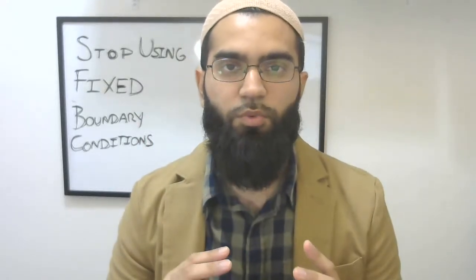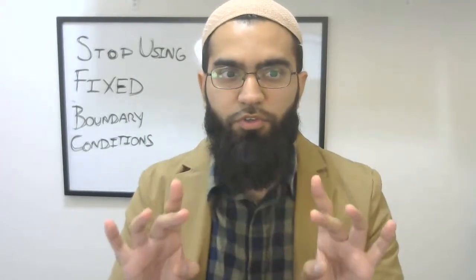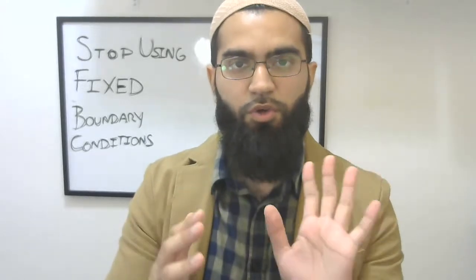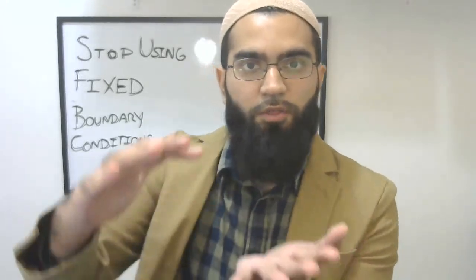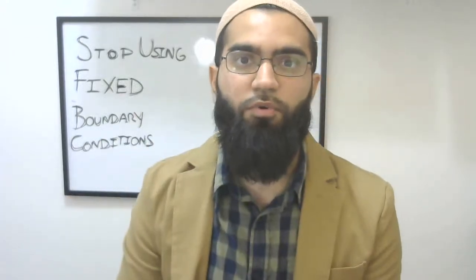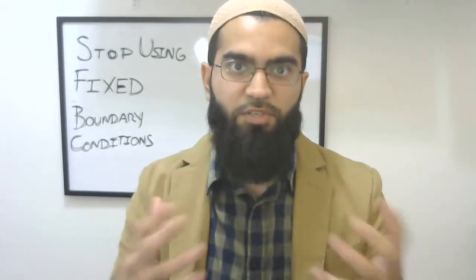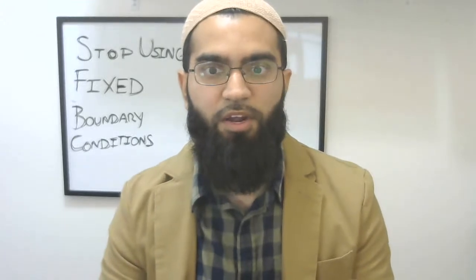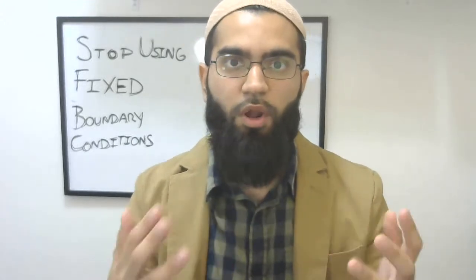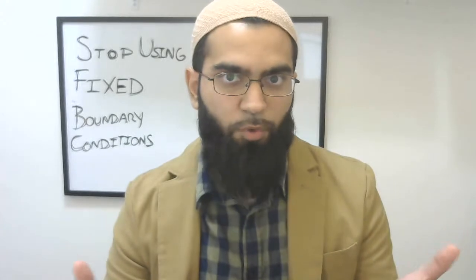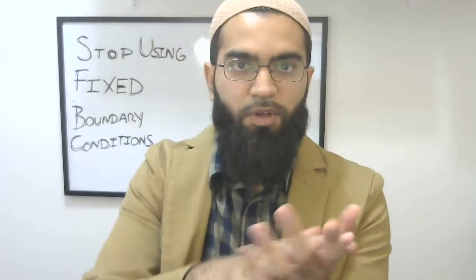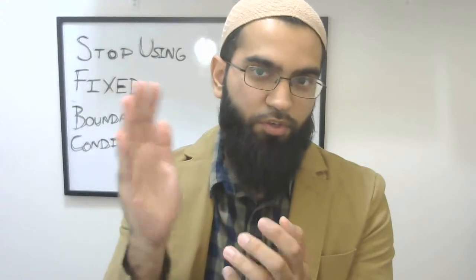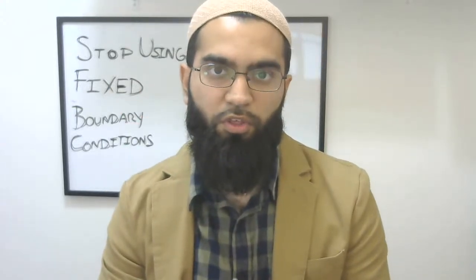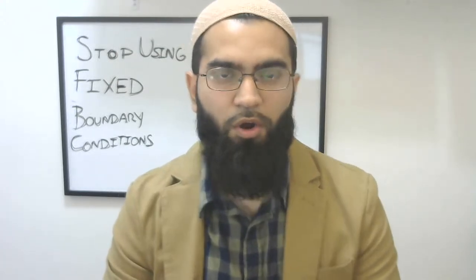But what's the difference, why the voltage was so low, was because the engineer doing the simulation used fixed boundary conditions on the bottom of the disk and then applied the force. So what? You need fixed boundary conditions in order for static finite element analysis to work and run. So you have to apply it. So they fixed the bottom of the disk and they applied a force, and they expected the voltage that they would get from the G coefficient or other methods of calculating that. However, there is something inherently wrong in that assumption.